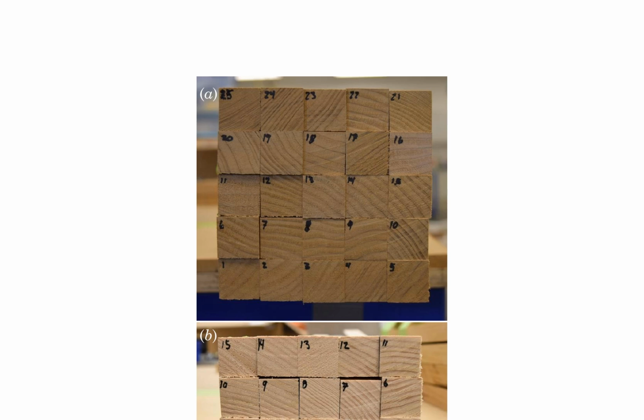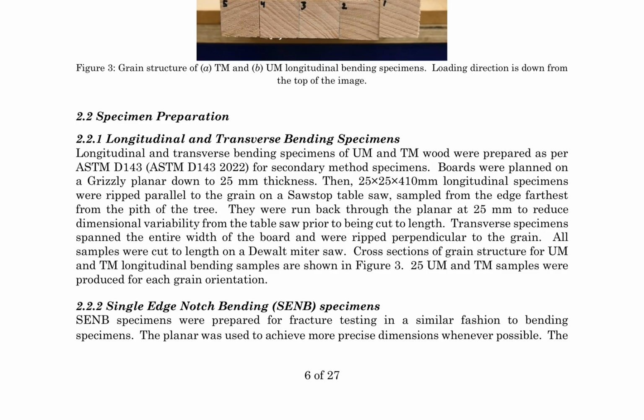Transverse specimens were also prepared by ripping them perpendicular to the grain, spanning the entire width of the board. A total of 25 specimens were produced for each grain orientation. The paper also presents the grain structure of both untreated and thermally modified, TM, wood and longitudinal bending specimens, as shown in Figure 3. The loading direction is down from the top of the image. This figure highlights the differences in grain structure between untreated and TM wood, which could potentially impact their mechanical properties and behavior under various loading conditions.